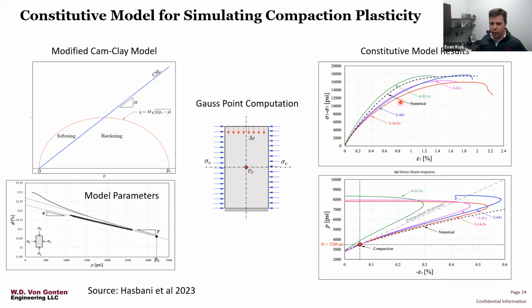Here, what we're doing is the constitutive model uses a modified cam clay model, which is this elliptical failure envelope constrained by the critical state line, and the data of reduction in pore volume and how the hardening behavior occurs comes from the Vaca Muerta data itself, notably during these hydrostatic cycles that we do prior to the triaxial stage.